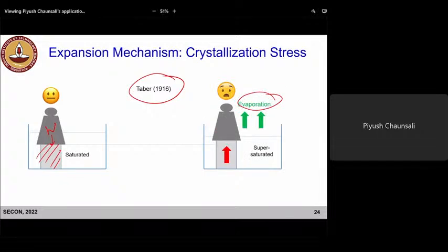This solution became supersaturated, meaning the concentration of ions increased, right? Because water must have evaporated. So this solution became supersaturated. That led to crystallization of the salt, and that crystallization pushed this weight up. So this induced crystallization stress.